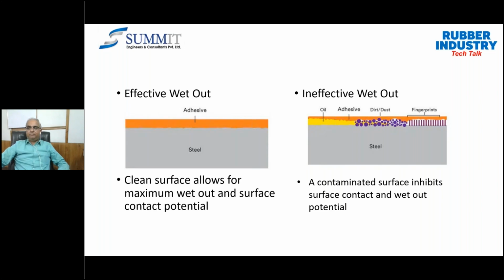Okay, and they are prone to behave erratically or differently when it comes to attracting the moisture or attracting the liquid. Okay, I will talk a little more about this once I finish this ineffective wet-out. Now you can imagine, if your o-ring or the substrate has some kind of dirt, what will happen? There is going to be oil or dust and all. So the effective area or the effective contact potential has been reduced to the minimum, and thereby it is going to create a problem, that is your bond failure.